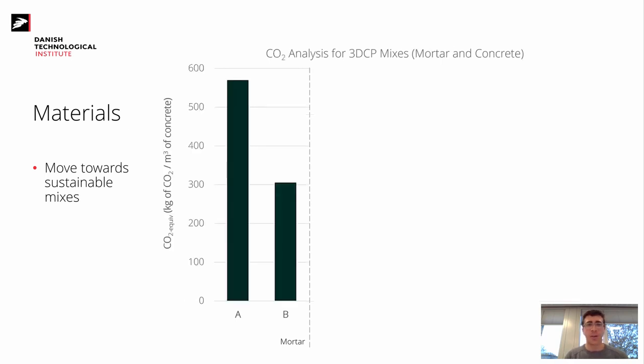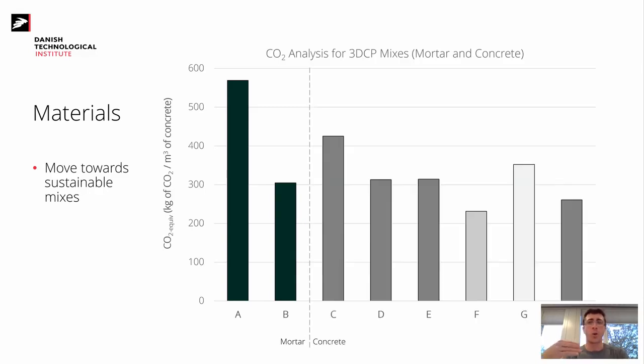Now, when you look into the CO2 equivalent of these materials, as you reduce cement content, you have a dramatic reduction of the CO2 footprint of these mixes. We were in the order of almost 600 kilos per cubic meter. The second mix is quite specific. Again, we use the calcined clay cement, so we could increase the amount of limestone filler in the mix. But that detail aside, when you go towards concrete, and all of these mixes are using either CEM I or calcined clay cement, you have a dramatic reduction of CO2 equivalent. And if you look specifically at mix F, it's the only one you can compare to mix B because they both have the same cement type, calcined clay cement. Therefore, by default, you already get about 30% reduction on CO2 compared to CEM I.